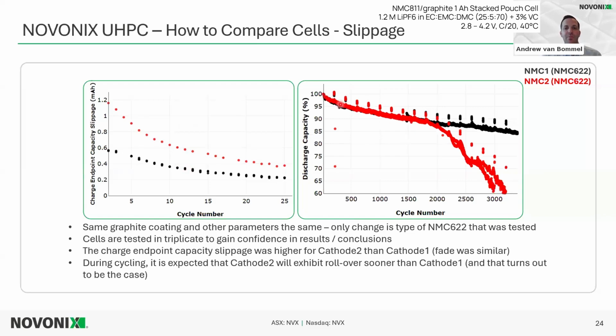And you can see this is the case. So the rollover occurs after 2,000 cycles. You see more quicker rollover from the red cell than for the black cell. So this method of determining, or comparing, when rollover will occur is an excellent way of using UHPC. You cannot predict from these normal cell metrics when that rollover will occur, but using UHPC will give you some good evidence comparing cells and when they would roll over.